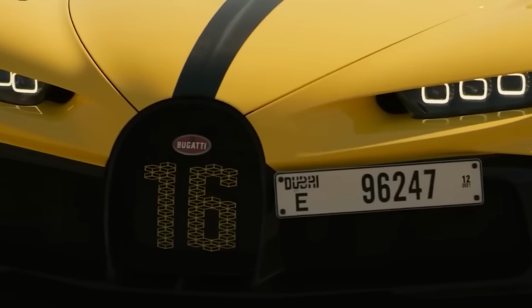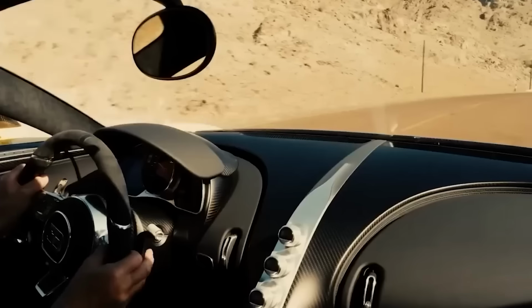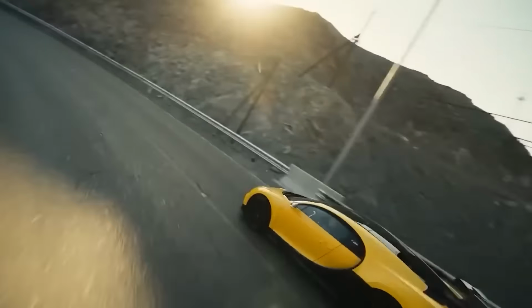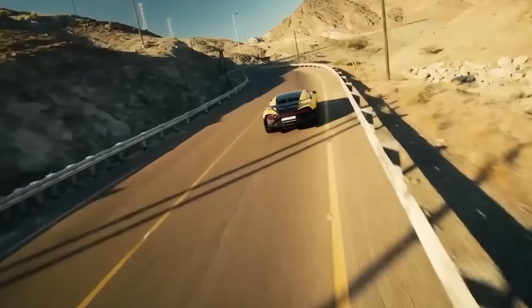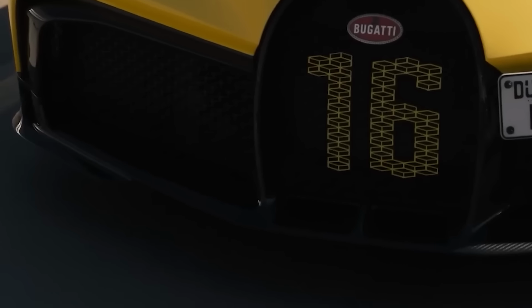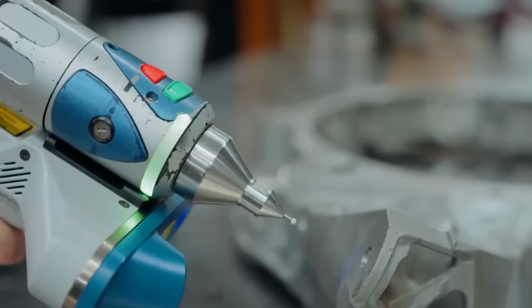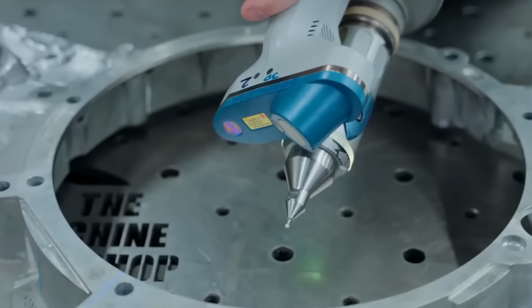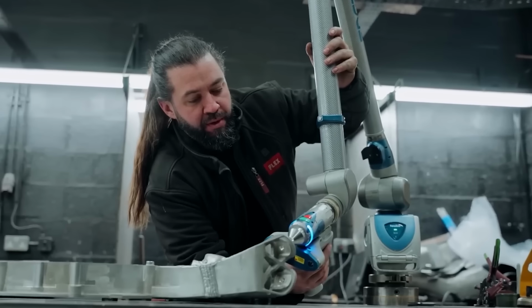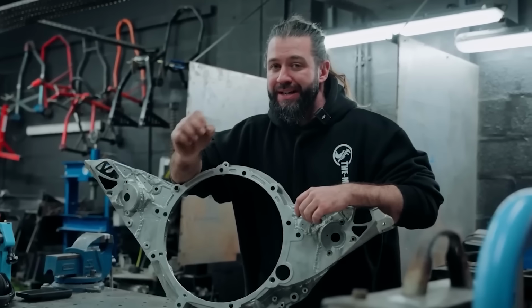With the welding finished, Bob sets the mount aside and surrounds it with welding gloves to retain heat. The part needs to cool slowly. A rapid temperature drop after welding could introduce warping or residual stress that undoes everything. Controlled cooling, gradual and even, is the final step in the process.